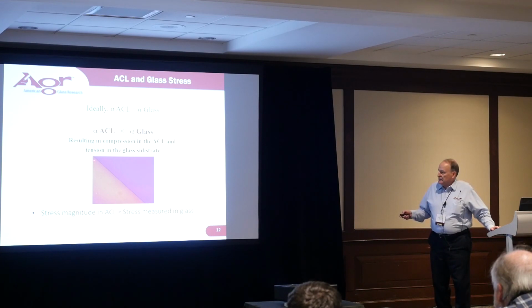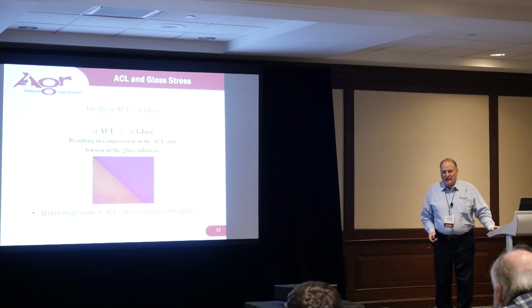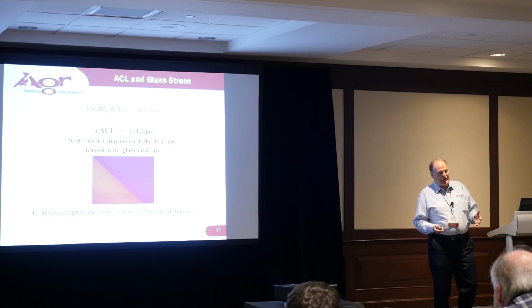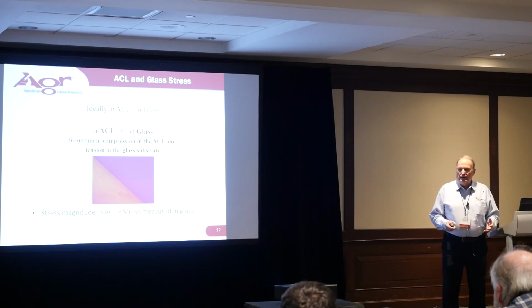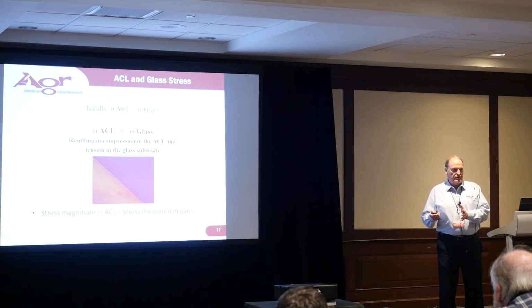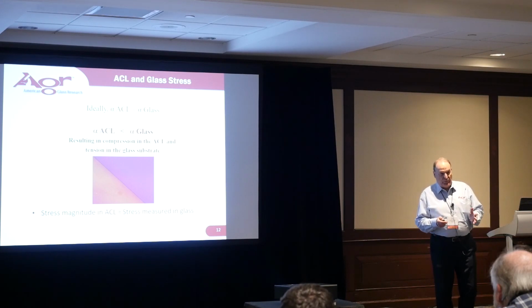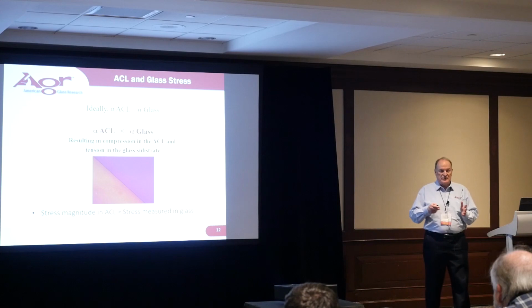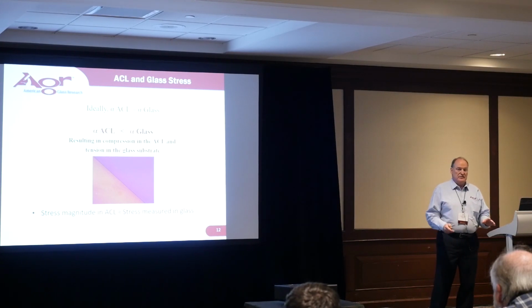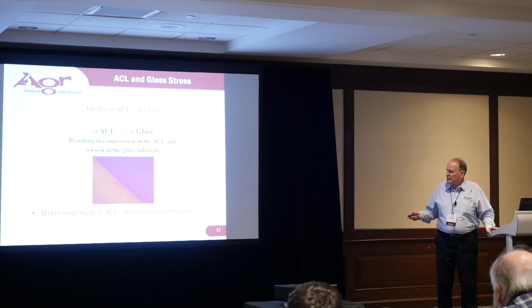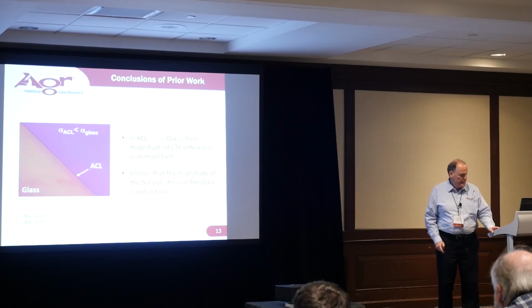So we would like to have our ceramic label in compression, but now we become a little problematic here. If this tension stress in the glass becomes excessively high, well, then that can go back to our fracture equation or our criterion: if we have too much permanent tension stress in the glass, that could start to add with the tension stresses created by other types of loads. And so we became very concerned about this magnitude of the tension stress that's in the glass.